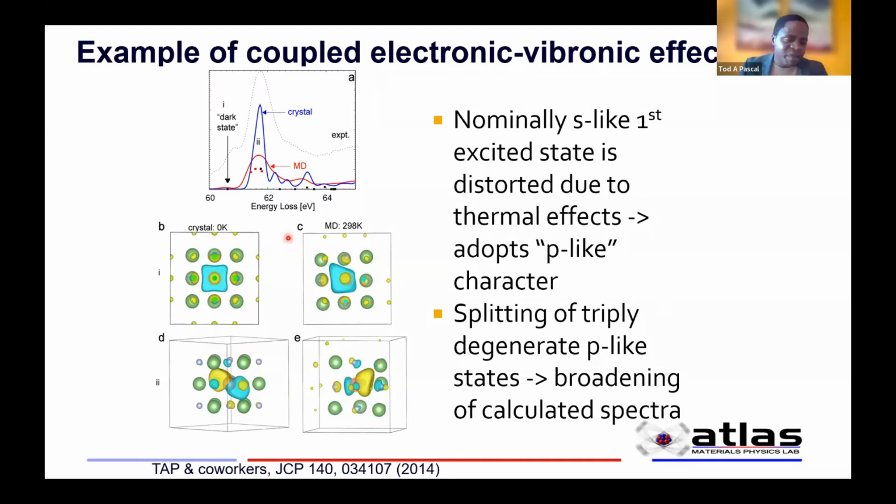So this was particularly interesting. We showed about 10 years ago that this happens not just in lithium fluoride, but in a whole bunch of other lithium compounds, lithium nitride, lithium oxide, and so forth. Some of the times we see the dark state because it's at low enough energy that you can actually resolve it, and other times it's there, but close enough to the main transition that it's hidden. You do see in a lot of these compounds a change in slope right at that first transition.